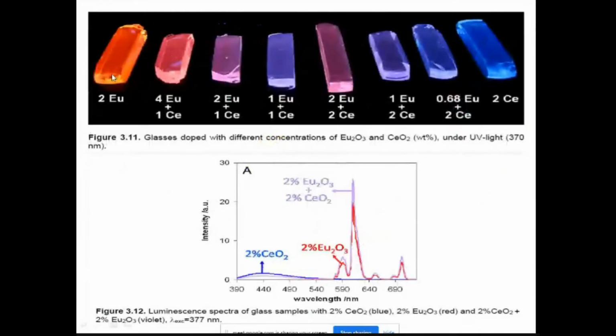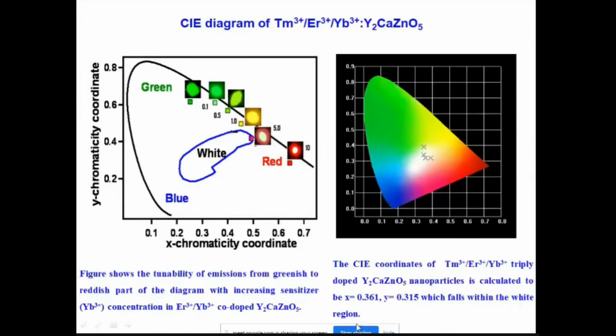And similarly, europium is the red color, cerium is the blue color, and by keeping on adding these two atoms and changing their composition, I am able to tune red to blue or blue to red. And this is the emission spectra. And now, my dear friends, look, there is one nano phosphor we have prepared: yttrium calcium zincate, with thulium, erbium, and ytterbium. These three elements are giving three colors. I kept the yttrium calcium zincate constant, and I kept the thulium and erbium constant. Only I am changing the ytterbium concentration. When I change only the ytterbium concentration, I am able to tune from green to red. This is the research we are doing.